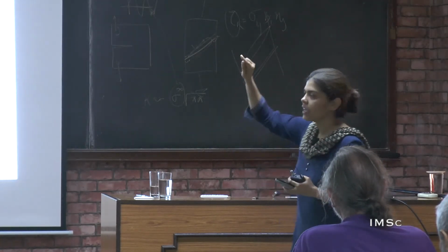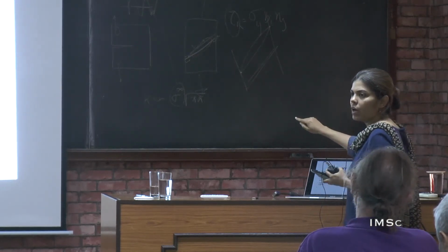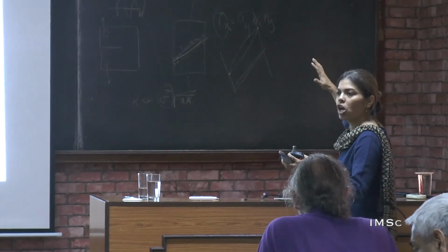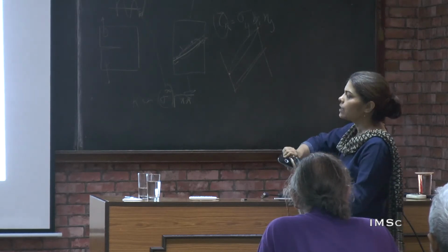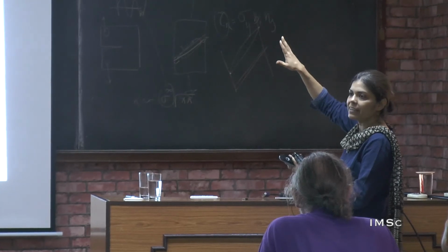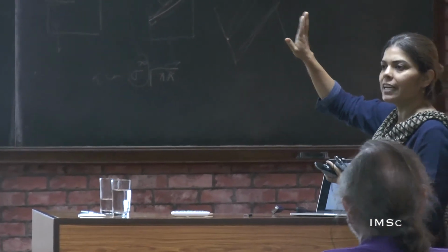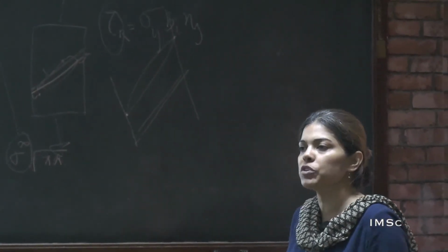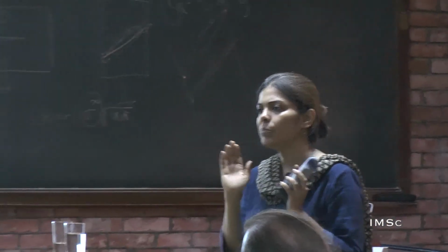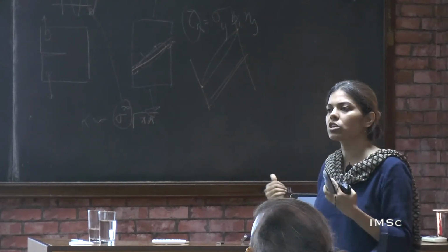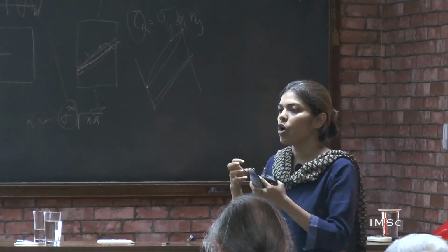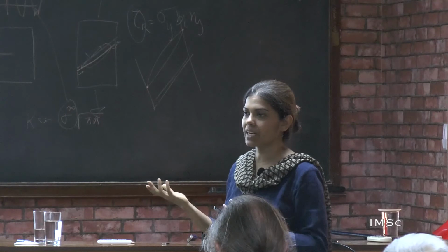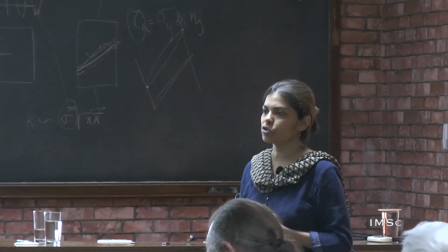So if you have a zigzag growth, if it grows like this, it should try to come back to the plane, which happens in an overall average manner. But if I look at specific planes, then I see that there is already a flat surface, a slip plane has formed there, and then suddenly they find the existence of each other, and there is a sharp joining of that. Now once you have a well formed crack, then it progresses sequentially towards the propagation direction. But this initiation process, which is only attributed to slip plane activity, is perhaps not right, it's microstructural examination based. It is not mechanistically possible that high opening stresses, as well as not allowing any form of dissipation like you are saying, which is high triaxiality, will not lead to damage growth.